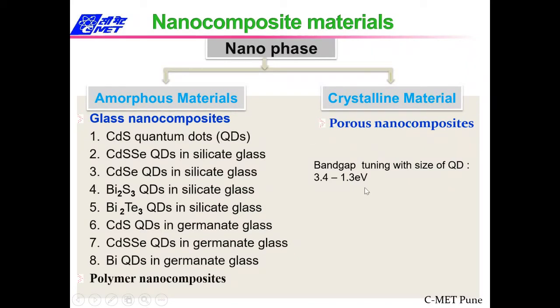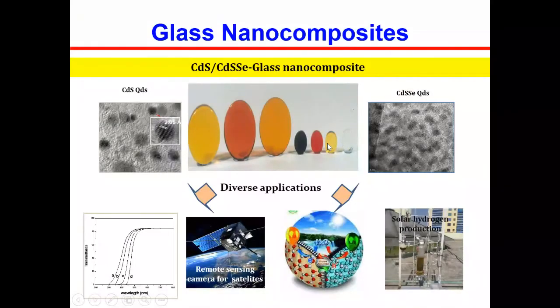And you can see the band gap. The band gap can be tuned with the size of this material. Suppose cadmium sulfide of 1 nanometer, 2 nanometer, 3 nanometer, 4 nanometer gives different band gaps. So we can tune the band gap from 3.4 electron volts to 1.3 electron volts with size in the glasses. These are this kind of glasses. There is no crystal here. This is CdS crystal inside, 2.5 nanometer. This may be 5 nanometer, this may be 7 nanometer. So you can see that there is a change in the band gap.